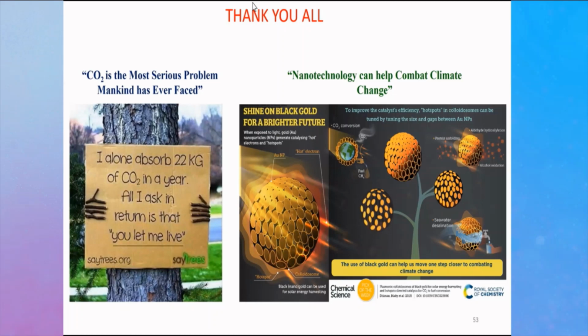How are you quantifying the effect of photothermal heating on carrying out a CO oxidation? If you only want to know the photothermal heating, you find out what temperature you achieve in the photothermal reaction. Let us say I take a reaction mixture exposed to sunlight, and the temperature of the reaction mixture is 80 degrees Celsius. Now you do another reaction in the dark with no light at 80 degrees Celsius and see whether it is really a photothermal effect, or whether it's the hot electron or the electromagnetic field that is playing a role in plasmonic catalysis. Most of the time it's not a photothermal effect, but in addition to that, it's the gold plasmonic which makes a huge impact on reducing the activation energy of these catalytic reactions.